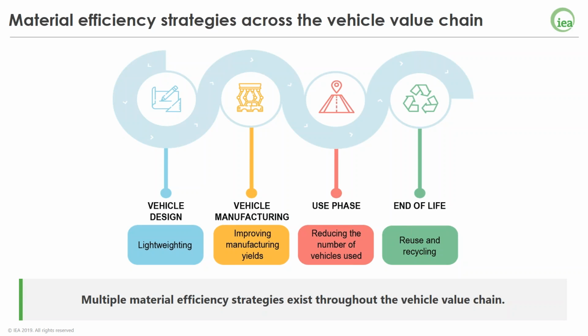Another strategy is to improve manufacturing yields. Currently, considerable amounts of steel and aluminum are being lost during the manufacturing of vehicles, with typically about 70 to 80% of steel and 80 to 85% of aluminum entering the manufacturing plant ending up as part of the vehicle. These are some of the lowest yield losses among end-use applications. The losses occur in part because the quickest and most effective manufacturing methods are used. Giving a priority to material use reduction could improve these yields.